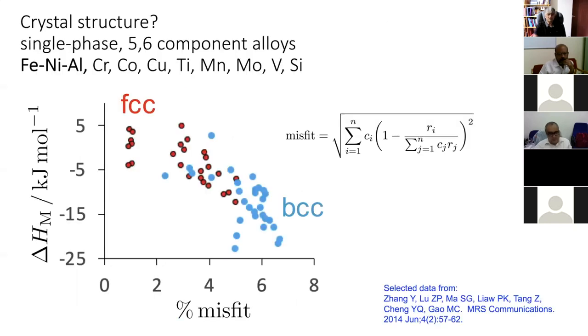Now, this is another plot where we have the enthalpy of mixing here and the percentage of misfit that I explained earlier in an earlier diagram. And this is for all of these elements in five or six component high entropy alloys. And the argument was that at this point we only get FCC, and at this point we only get BCC, but look, there's an awful lot of confusion here, where we get both FCC and BCC. So I personally don't think this is a good way of deciding whether you're going to get FCC or BCC or both.